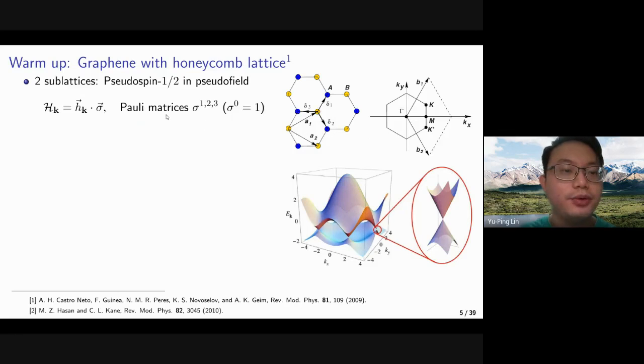So to do this, we can think of graphene as having a pseudo-spin 1/2, which corresponds to the two sublattice sides. And the Hamiltonian will take a 2x2 form, and it could be thought of as a pseudo-spin in a pseudo field, which takes this form. It is a coupling between an h of k inner product with sigma, where sigma is the Pauli matrix. And you can think of it as an analogy of the spin 1/2 in the magnetic field.